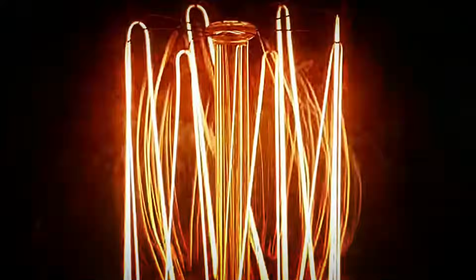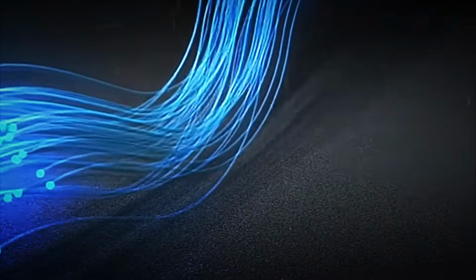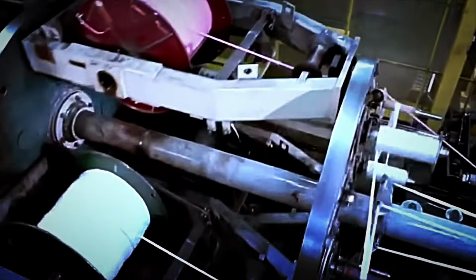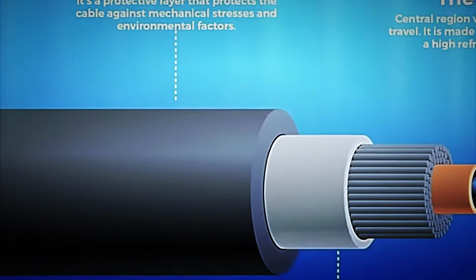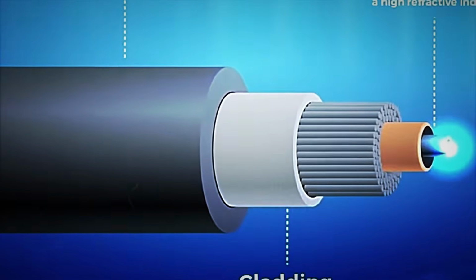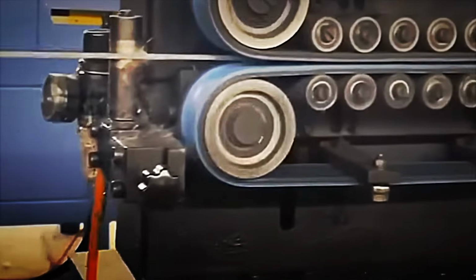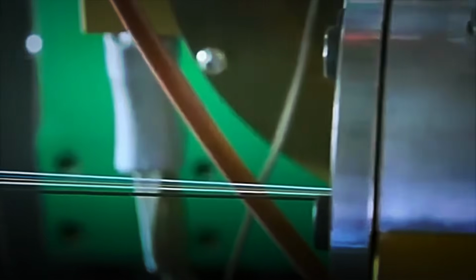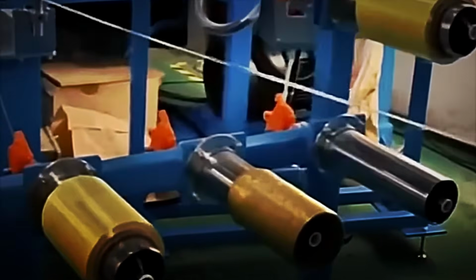Producing kilometers of continuous fiber is not enough. Every meter must meet international standards that guarantee stable data transmission. Multiple optical and mechanical tests are carried out in this section. The first check is attenuation measurement. Laser pulses are injected at one end, and the amount of energy reaching the other is measured. The allowable loss is minimal. Any deviation indicates internal micro-defects that scatter the light. Fibers that do not meet the standard are automatically removed.